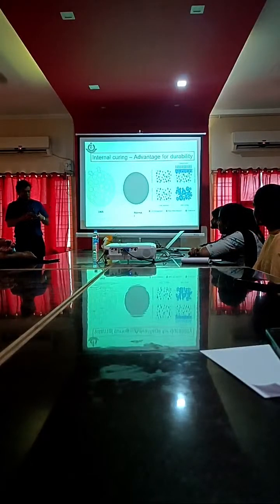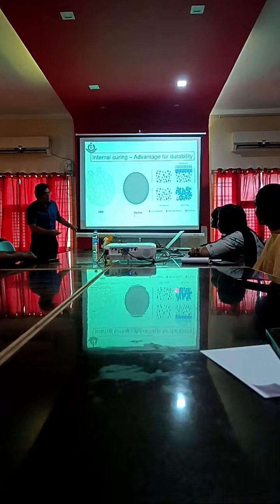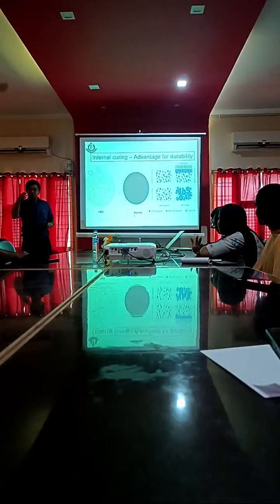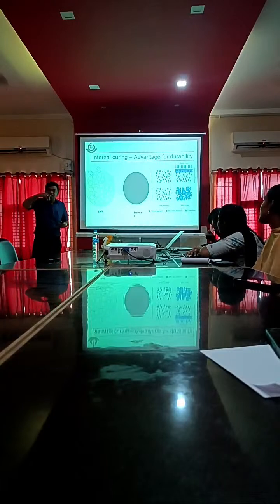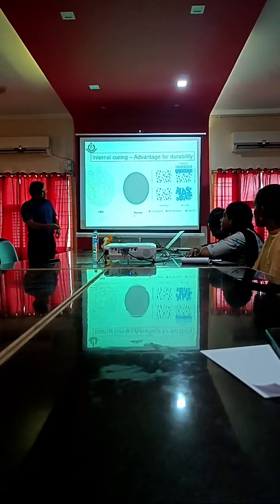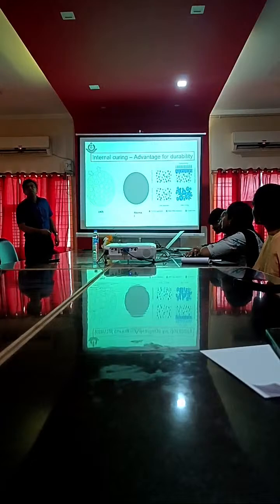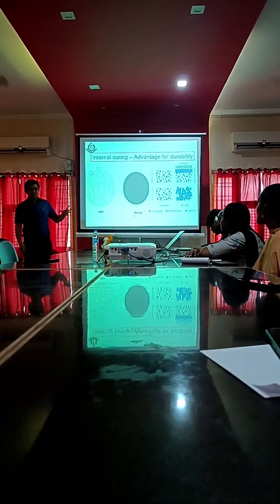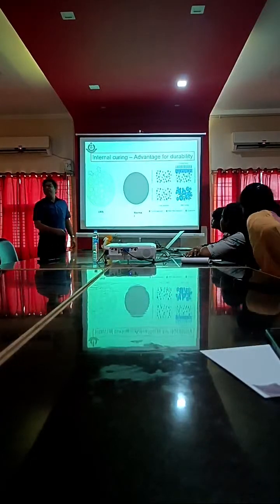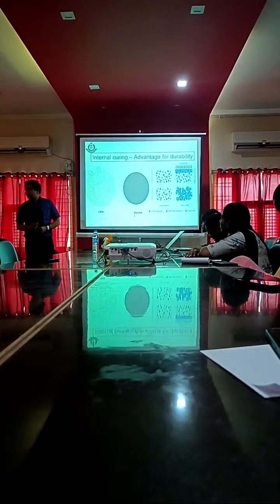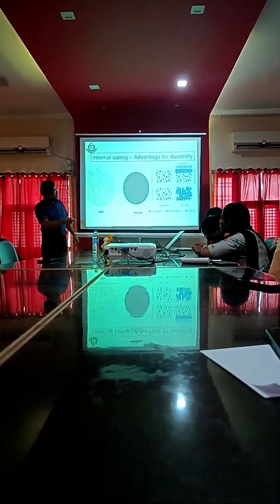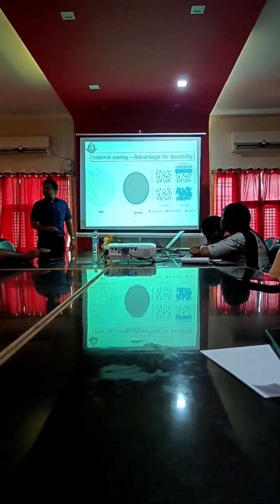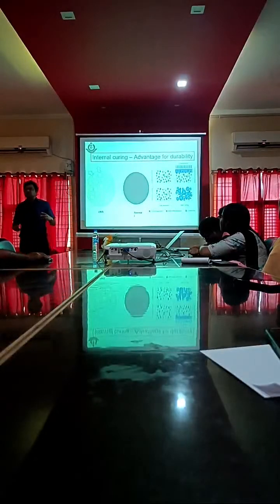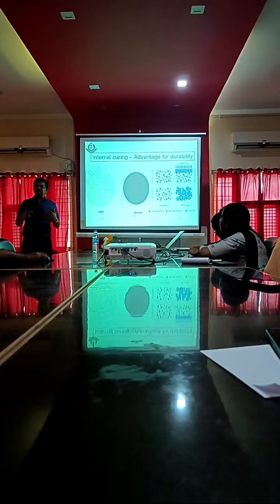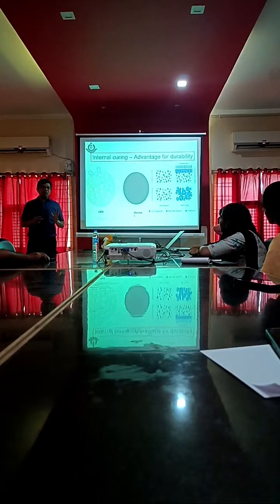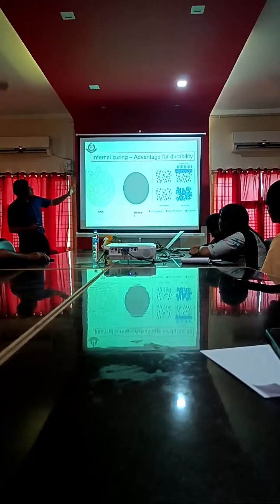After the concrete becomes hardened, what happens? This water comes out from those pores. The aggregate which absorbed this water releases it from the pores, and what it does is internal curing. You understand? It facilitates internal curing, that is the beauty of this material. Whereas that is not the case with conventional aggregate. Okay, so if you use this aggregate, it doesn't require any curing as well. It does this internal curing automatically because of the porous structure. That is one advantage of that.